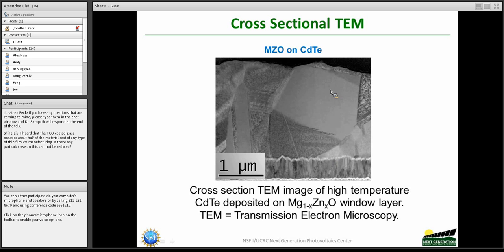And here is the cross-section TEM of a device. Here is the magnesium zinc oxide layer in this white region here. Here is the cadmium telluride, and this is one large grain that goes from the magnesium zinc oxide to the back.